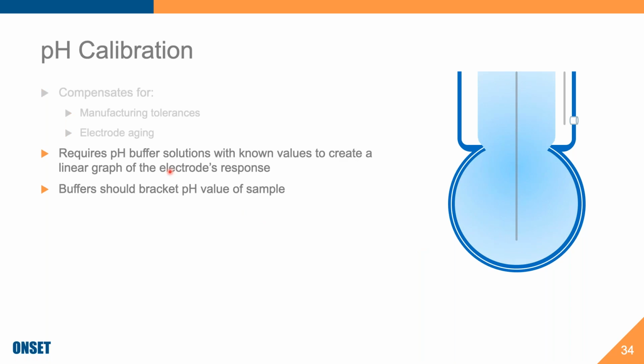Okay. pH calibration requires specific pH buffer solutions, and it depends on the manufacturer. These buffer solutions have known values, and they're meant to create a linear graph of the electrode's response. This graph will be potential versus pH unit. Depending on the manufacturer of your meter or your logger or your sonde, you'll have hopefully at a minimum 2 pH buffer solutions recommended by the manufacturer, and maybe 3, and there are 3 standard ones that a lot of people use. That's 4, 7, and 10. But for different applications, you might require different calibration buffers, so you'll want to make sure that you are using the correct buffers.